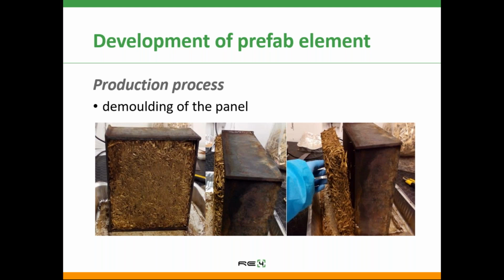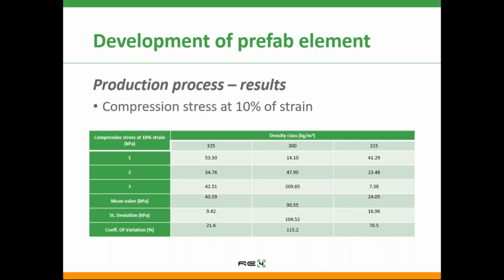The process optimization was related to the bulk densities of the panels in order to achieve the desired insulating performances. Physical and mechanical properties of the produced wood panels were also investigated. In fact, in this slide you can see, for the obtained panels divided by class of density, the compression stress at 10% of strain.